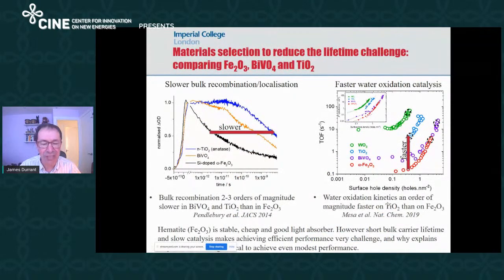If we start to actually drill down now to real data, this just gives an example of kinetics for three oxides: hematite, bismuth vanadate, and titania. On the left, we have plots of the optical signal of the charges as a function of time on very fast timescales. This is a log timescale going from a picosecond out to a few nanoseconds. And the decay is essentially because this is a bulk material. These are the decays of the bulk charges in those materials.